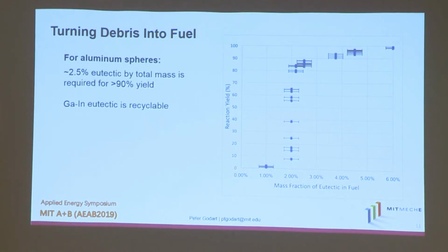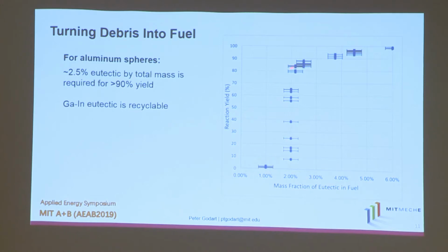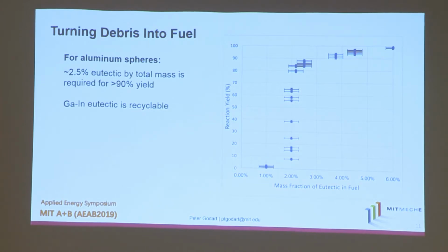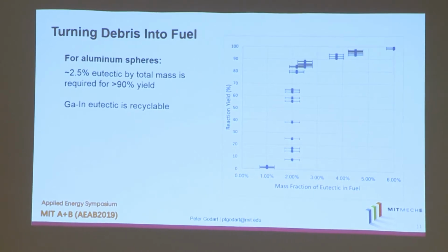And so how much gallium and indium is required? Well, we discovered that, and this plot here shows reaction yield, which is how much of the aluminum has reacted to produce hydrogen, versus the mass fraction of eutectic gallium and indium in the fuel. And we've discovered that you only need about 2.5% to get to that 90% reactivity yield. And that if we increase it to about 4.5%, we're now over 95% reaction yields. And because the gallium and indium is not consumed in this hydrogen generation process, the eutectic is actually recyclable, and we can use it to make new fuel again.